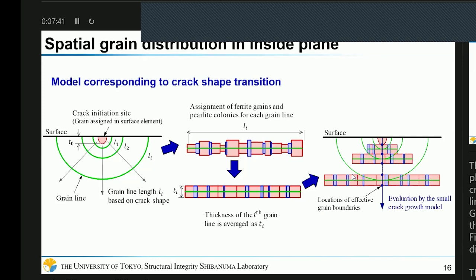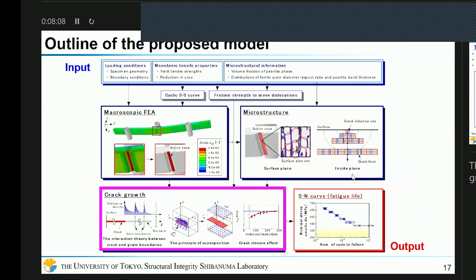And the spatial grain distribution in the inside plane is modeled corresponding to the crack shape transition, as shown in these green lines. And we assign grains on each line, and the thickness is averaged. And then we obtained the spatial grain distribution in the inside plane like this. That is a microstructure model. It's very simple. And the last model is crack growth.